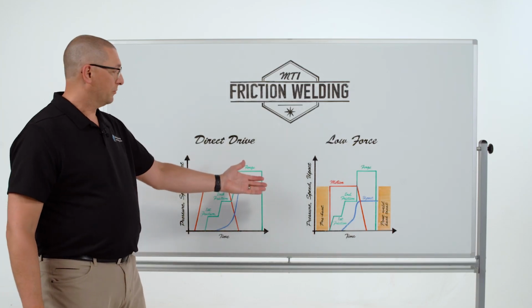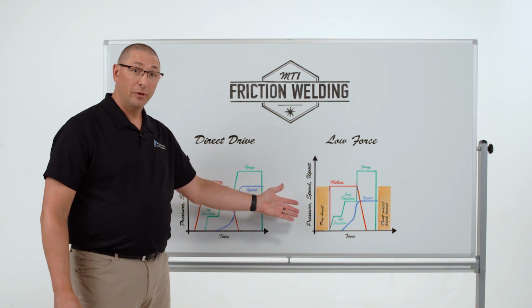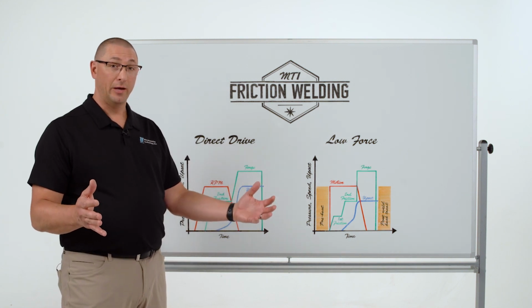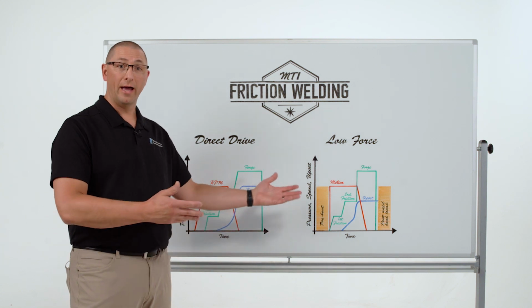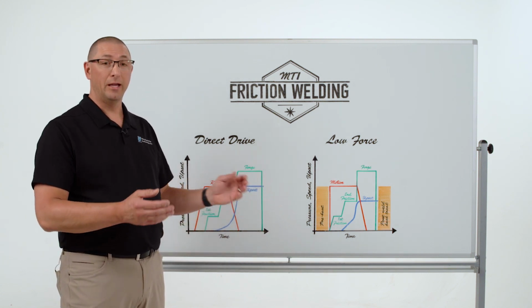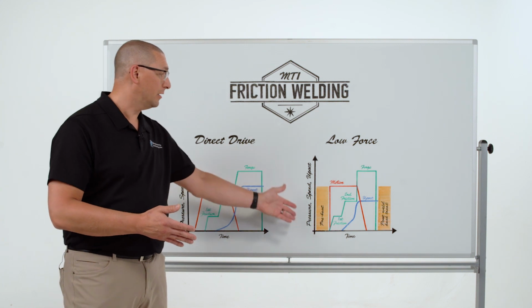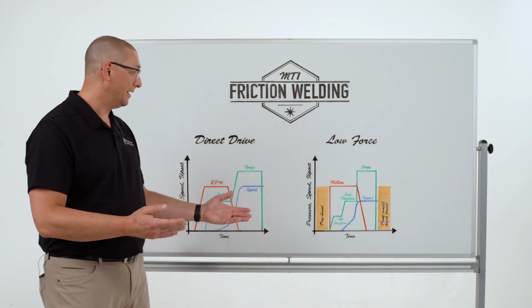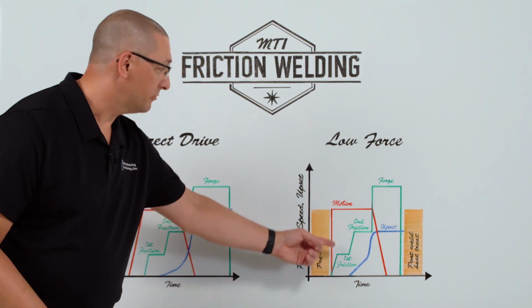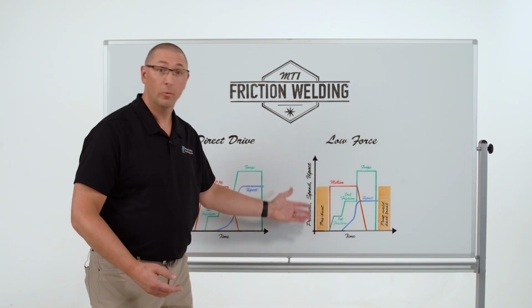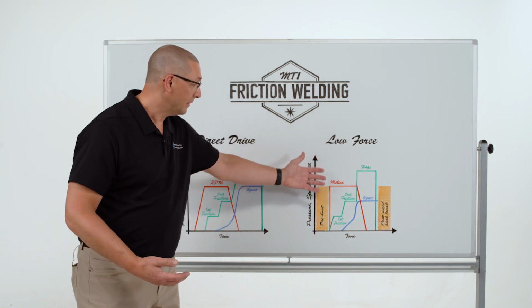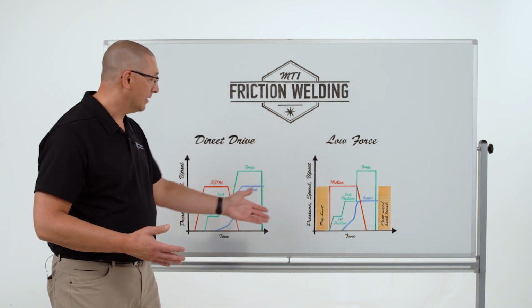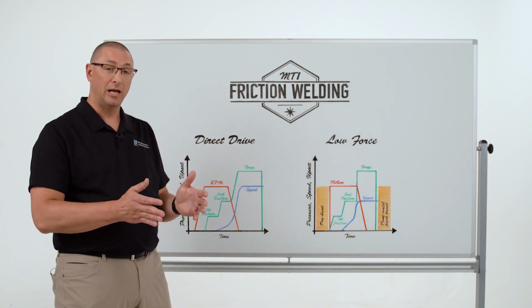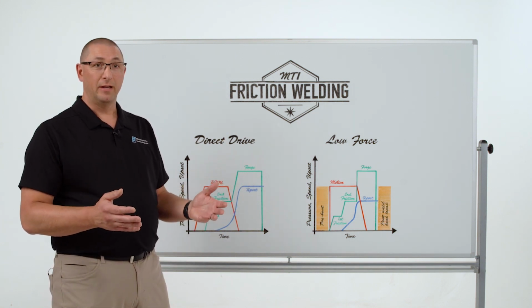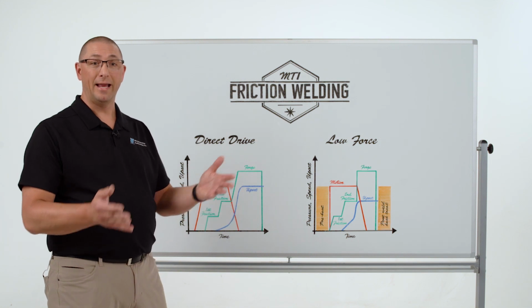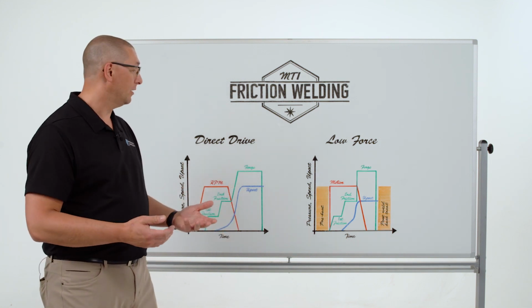If we look at the low force process, we have the ability to add preheat so we can get the heat soak into the part that we want without having to generate all that friction or all of the upset. We can make low upset welds with this because we're using the preheat to get the heat in. So we may go through a first friction phase, we may go through a second friction phase, or we could just bring on forge force from the beginning and just handle all of that heating with the preheat side. So now our cycle times are much lower, but the biggest benefit is we may not create all that upset that then has to be turned off in this post-weld machining operation.